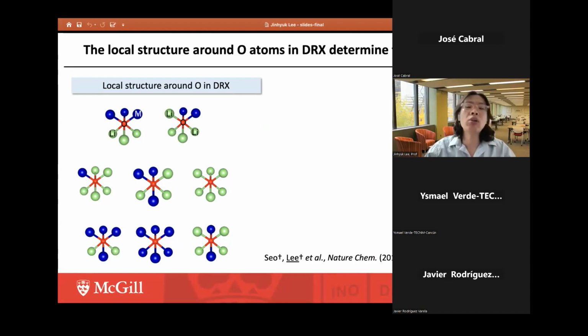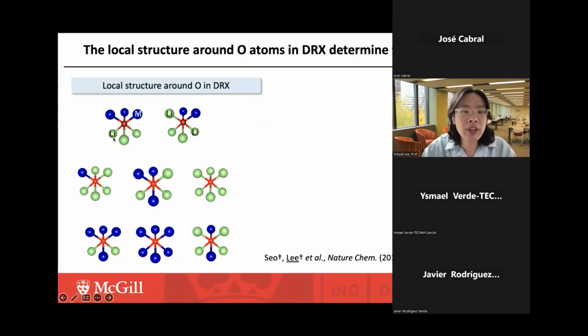So imagine the DRX structure, like I said, the cations are nearly randomly distributed in the cation FCC lattice. And it is interpenetrating with the oxygen lattice. So we can imagine that there can be many different types of local structure around oxygen. So for example, here on the left side, left top part, we are seeing the oxygen atom in the middle. This is denoted with the red atom here.